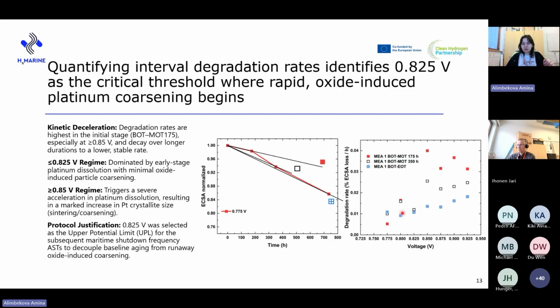Below 825 millivolts, the degradation proceeds a little slower, and here the aging is assumed to be dominated by very early stage platinum dissolution. As voltage increases, the degradation accelerates, and Ostwald ripening or particle coarsening increases, and the platinum crystallite size will also increase, as will be shown with the XRD analysis next.